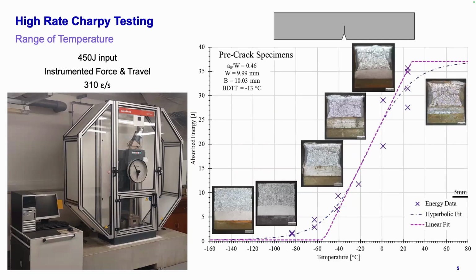We go up one level of constraint to the pre-crack system. So all of these have a very fine crack, showing the pre-crack face as well. Notice the energy value has massively reduced from the change in the a/W ratio, with the crack coming to 1/2 way instead of 20%. And we also have that transition.